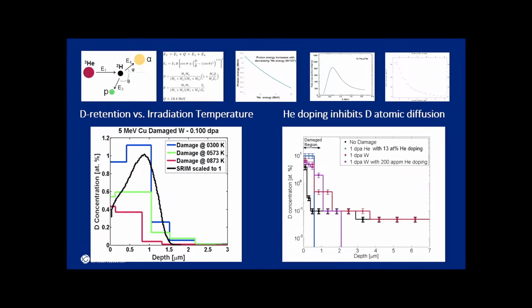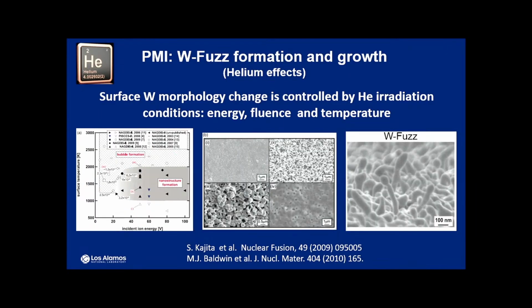And while I said helium was pretty bad for the mechanical properties, here helium actually helped to prevent deuterium diffusion into the deeper region. So when you have damage with helium versus tungsten, in this helium-damaged region you don't see much diffusion of deuterium to a deeper region. So that's one advantage.